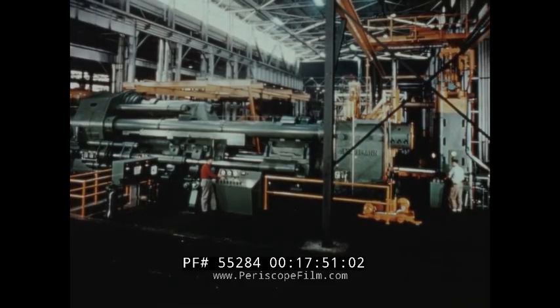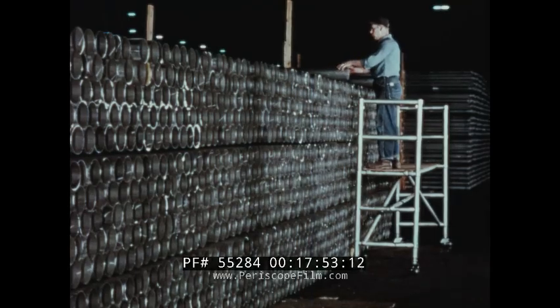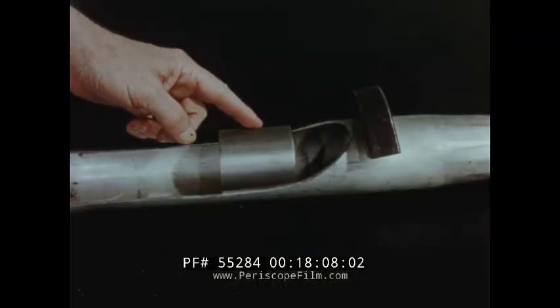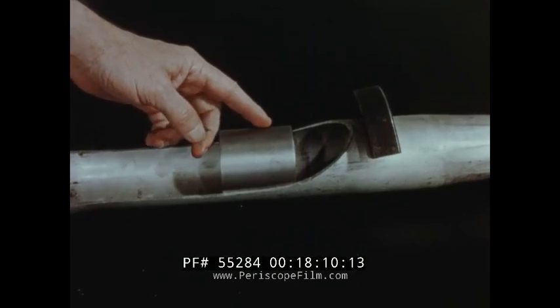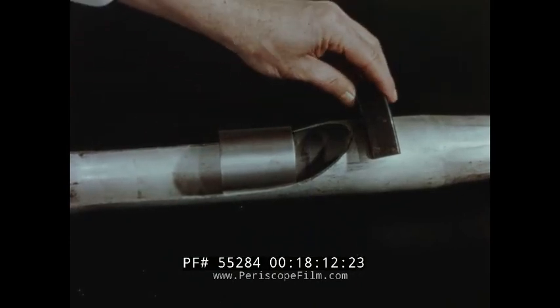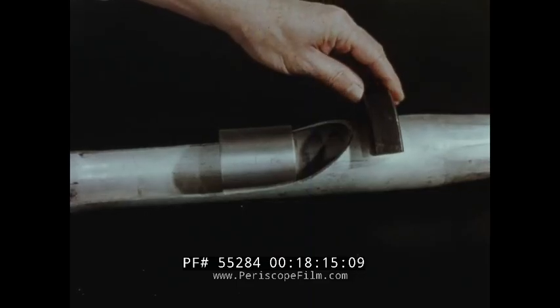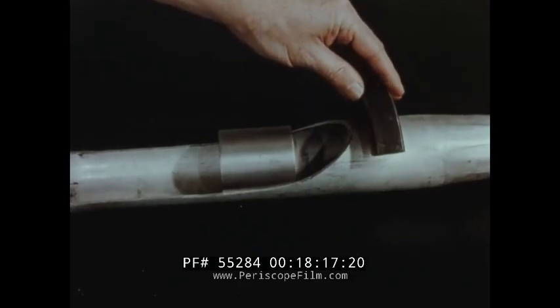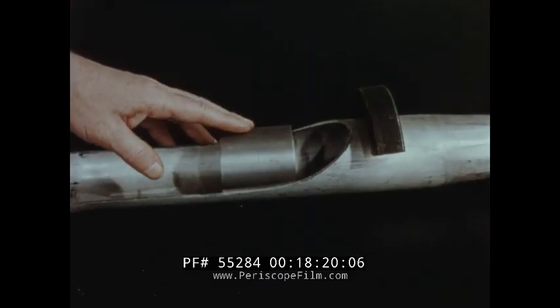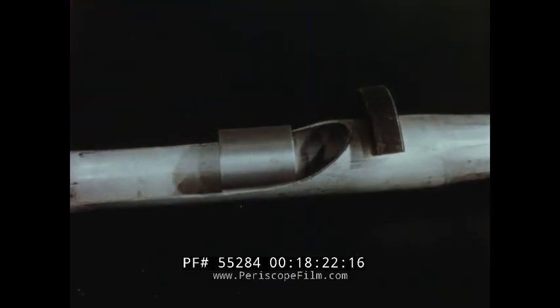The extrusion process is also used in the production of seamless tubing. Hollow ingots are placed on a bar or mandrel in the press cylinder. The mandrel controls the inside diameter, and the resulting extrusion is known as tube bloom. Now, this tube bloom is then placed over another mandrel on a drawbench and pulled or drawn through a die. The die determines the outside diameter of the tubing. The inside diameter is controlled by the mandrel. Several draws may be necessary to bring the tubing down to the desired dimensions.